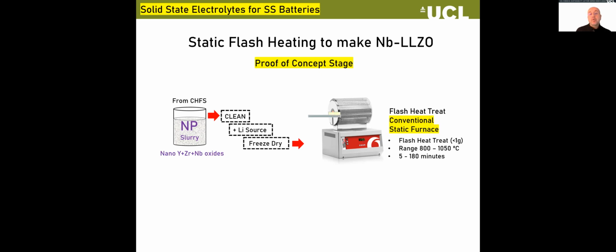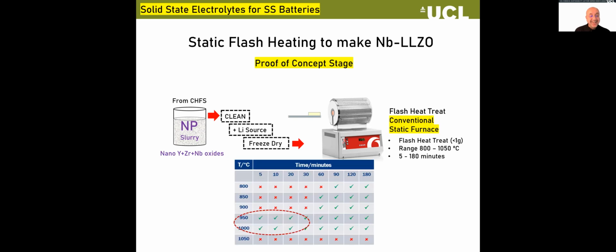And on each time, we would put in the sample of our powder, lithium mixed with these oxides, put it in our static furnace, and then take it out again. And we do that for different times at different temperature settings for the furnace. And you keep doing that. Okay. And what was really interesting was this, what we learned a lot.